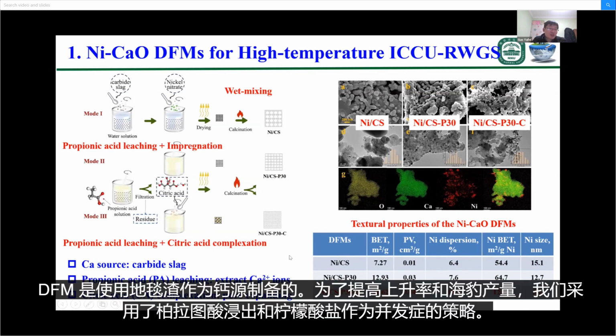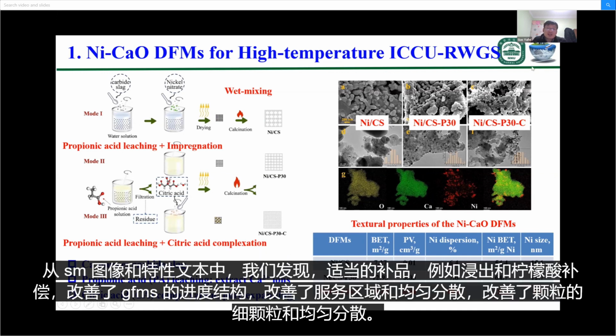The DFM is prepared using carbide slag as the calcium source. To improve its CO2 uptake and CO yield, we have employed the strategies of propionic acid leaching and citric acid compensation. From the SEM images and the texture properties, we found that the propionic acid leaching and the citric acid compensation have improved the porous structures of the DFMs and improved the surface area and calcium dispersion, as well as giving fine particles and uniform dispersion of the particles.